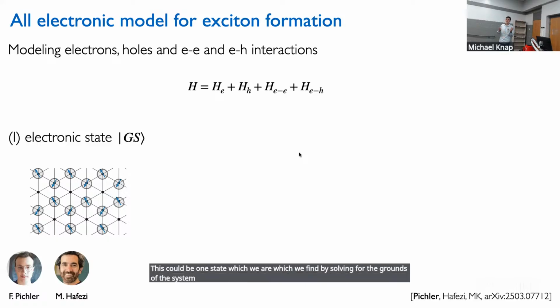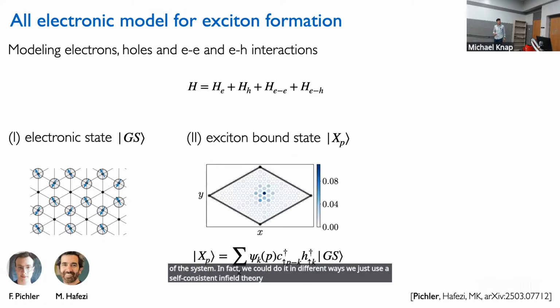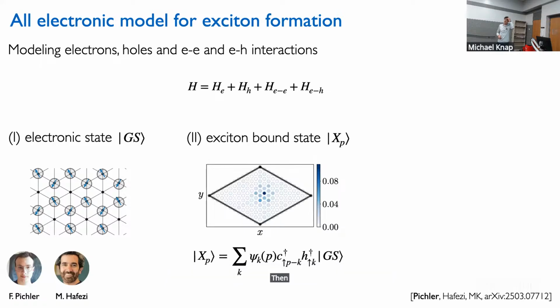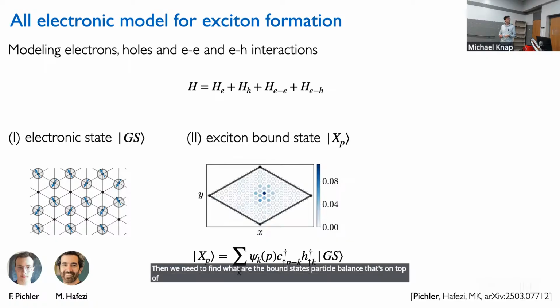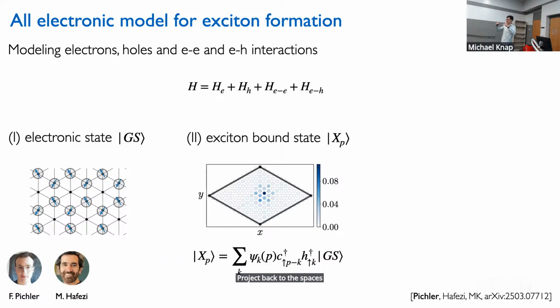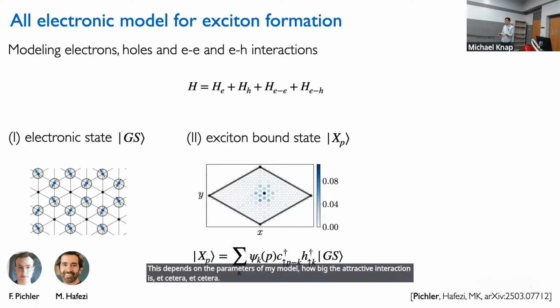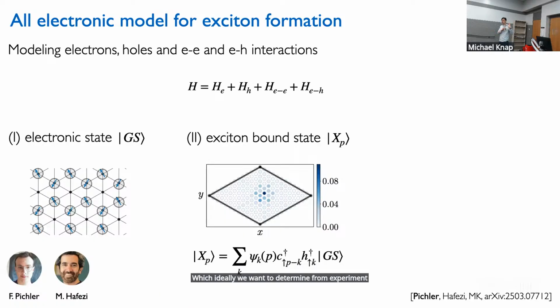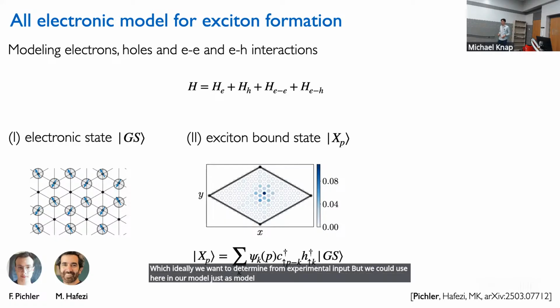In fact, we could do it in different ways. We just use a self-consistent mean field theory to solve for these types of states. Then we need to find the bound states, particle-hole bound states, on top of these correlated states. So we solve the two-body problem of an additional electron and an additional hole on top of the ground state, project back to this basis, and search for whether we find a bound state in the system or not. This depends on the parameters of my model, how big the attractive interaction is, etc., which ideally we want to determine from experimental input, but here in our model we just use them as model parameters for the moment.